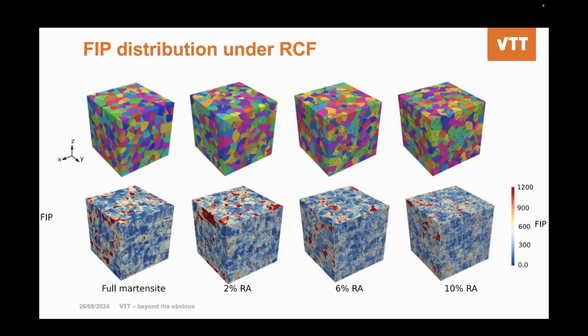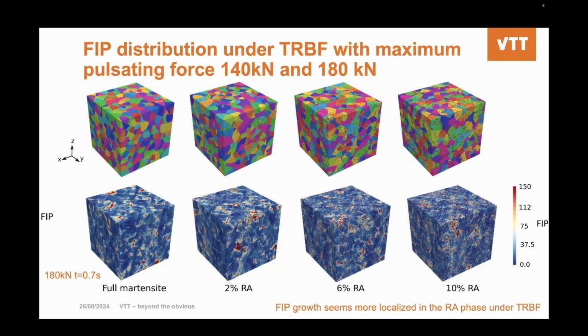Here are the results from the rolling contact fatigue, from full martensite structure to 10% retained austenite microstructure. We notice the FIP hotspots tend to gather around the grain boundary, but as the retained austenite volume fraction increases, it seems the localization has been mitigated a little bit. And here's the result from the root bending fatigue simulation. It shows very different behavior. All the FIP hotspots seem to happen in the retained austenite phase, not like the rolling contact fatigue.